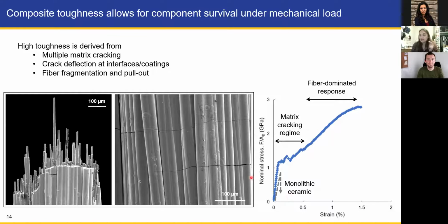So what happens is cracks are introduced into the matrix, and these cracks deflect around those really important coatings, and it keeps the fibers intact. So that allows us to increase our forces and stresses. What the fibers do is the fibers start to break and they can slide out of the matrix. And then when it finally fails, you get this really cool fracture surface where you have fibers that have been pulled out of the matrix. And that's what you see here. So this kind of messy fracture surface is exactly what we want to see, rather than a very flat, brittle failure that normal ceramics have.